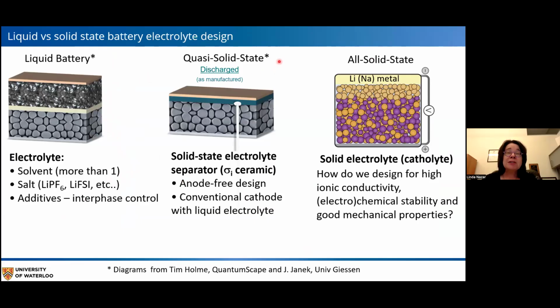This is an example of a quasi-solid state battery. This is a picture from QuantumScape. And this is the cell discharged as manufactured. And so the cathode side also has a liquid electrolyte, but on the anode side, there is a separator of some conductive ceramic. And this cell is designed anode-free, such that the lithium then comes from the cathode and deposits through the separator onto the current collector. So it's a conventional cathode with a conventional liquid electrolyte, but the difference is the ceramic ion-conducting separator.